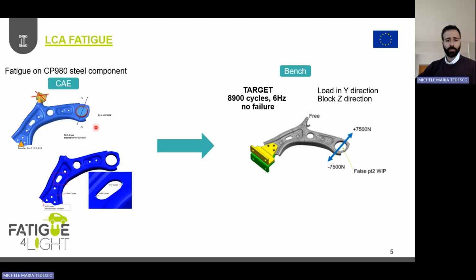Making the simulation, we have seen that the first crack on the component appears in this area. Afterwards, the most critical area is this hole, in which from the edges of the hole starts the cracking of the component, and after a second crack initiation in this area.